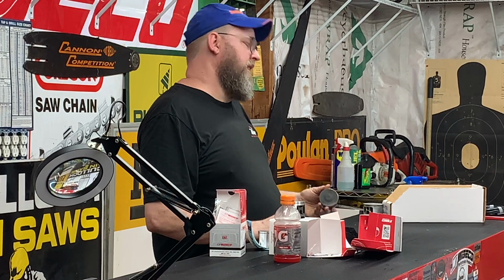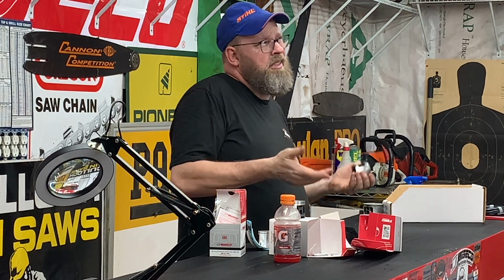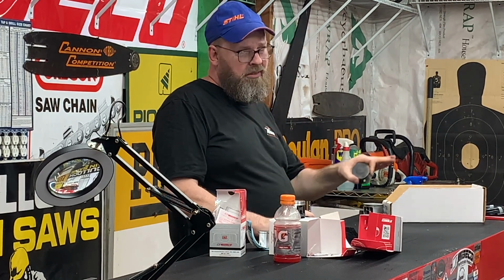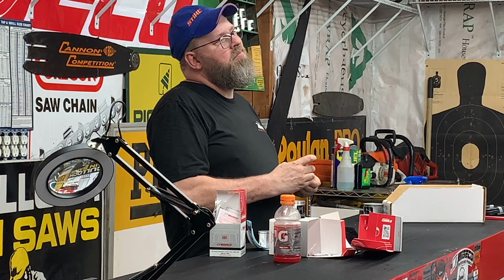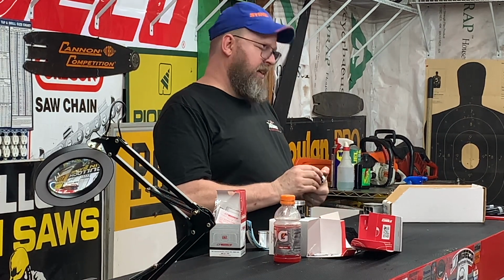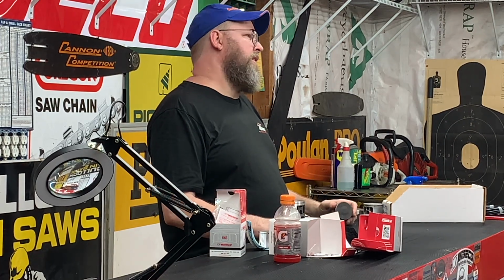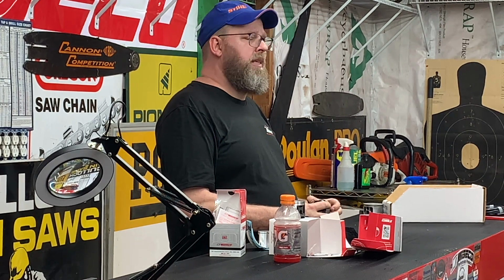That means it's been hot enough that as the ring moves, piston going up and down like crazy, hopefully in excess of 15,000 RPMs in a race situation, but hopefully less than 12,000 cutting firewood, the ring moving has pushed the pin into the body of the piston. Now, that hard pin is in there out of the way, and that hard ring can move wherever it wants. The opening gets next to a port, jams things up, destroys it. A lot of times you get lucky, it locks up before it destroys your whole top end. But in either case, remember, I told you so.